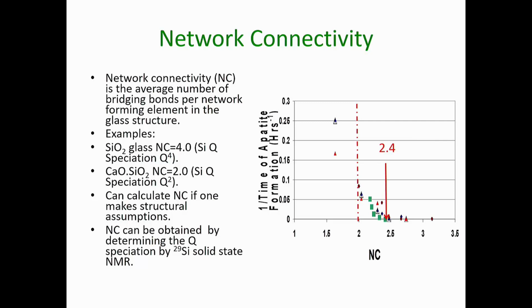In terms of the glass structure, we can actually predict how quickly a glass will dissolve by counting the number of silicon-oxygen-silicon bonds in the glass structure. And this we term the network connectivity. And the science here is perhaps a little bit heavy and complex for dentists, but essentially if we have a network connectivity close to 2, the glass will have its bioactive properties.